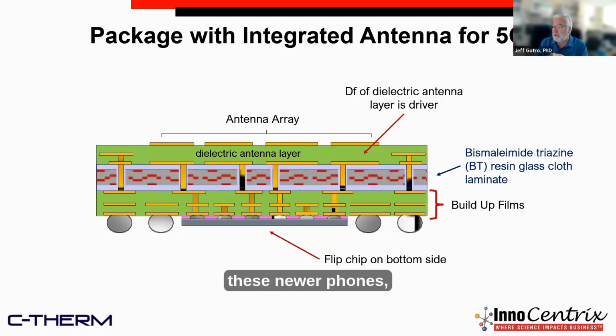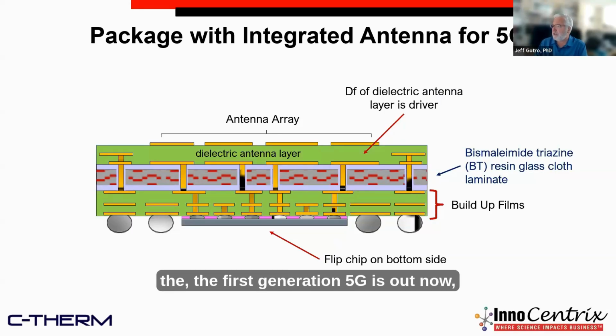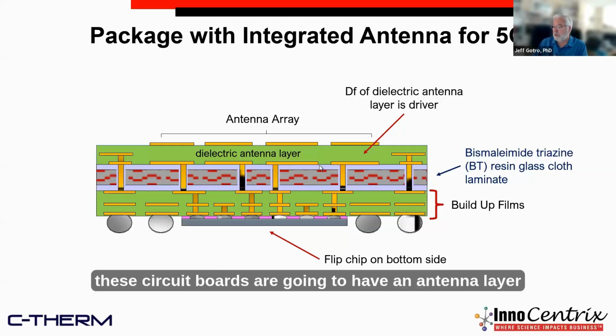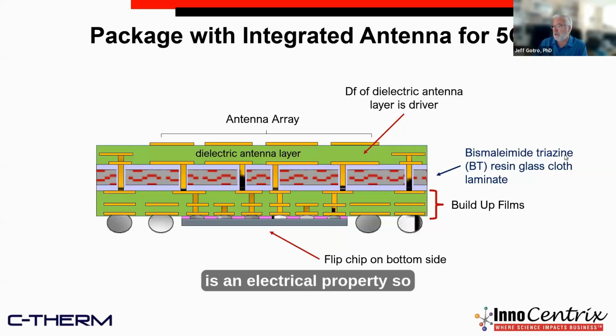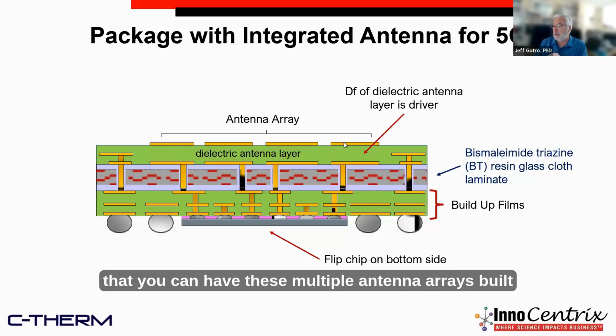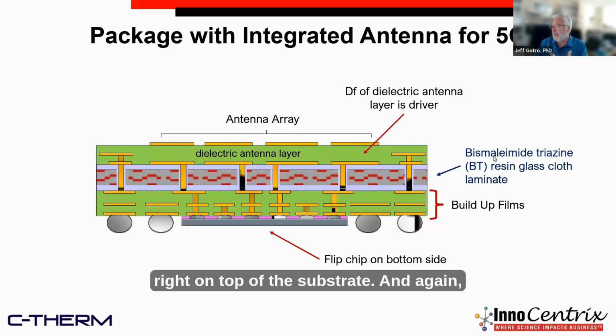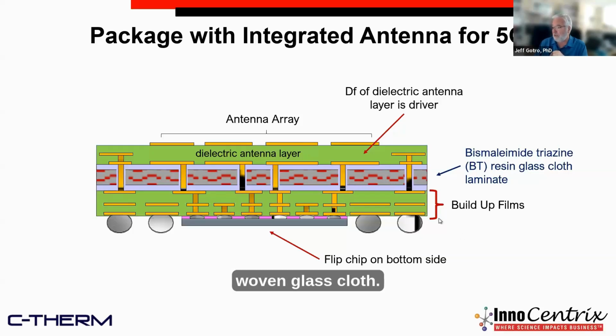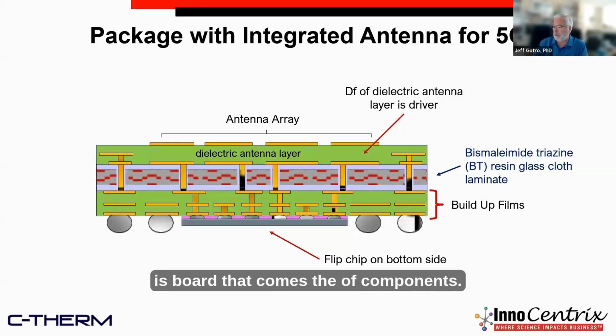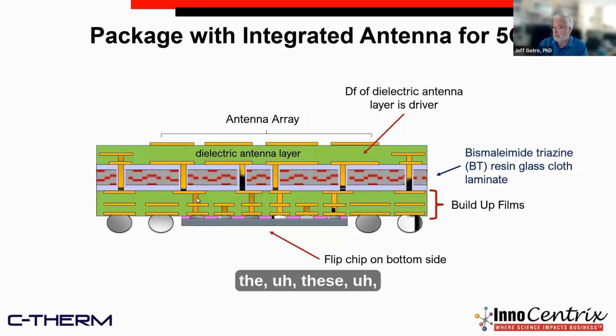Now, one of the things when you get into these newer phones, not the first generation 5G that is out now, but when we get into the next generation of 5G phones, these circuit boards are going to have an antenna layer built right in them. And so now we have these new polymers that have very low dissipation factor. DF is an electrical property, so that you can have these multiple antenna arrays built right on top of the substrate. And again, we have bismaleimide triazine (BT) resin with woven glass cloth. We have our buildup films. And now we have this chip that's attached to the bottom of this complicated substrate. And then these bumps go down to a main circuit board. So this would be like the main board in the back of your cell phone. And this structure would be mounted onto what we call the motherboard on the base of the cell phone.